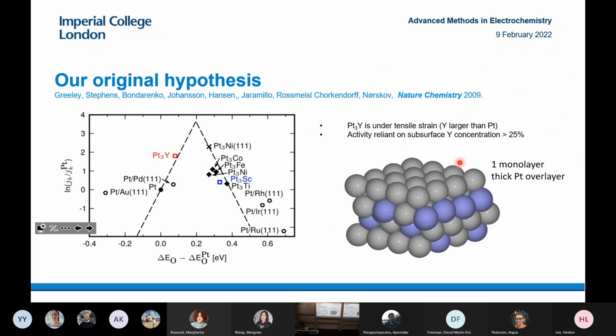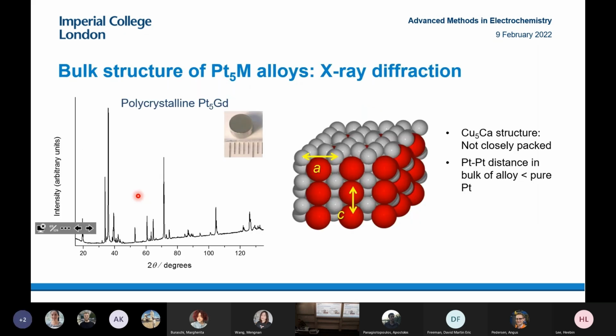So we originally expected, as I already mentioned, that this would only work if you have yttrium in the second surface layer, because actually yttrium is bigger than platinum. So we expected that if we had a pure strain effect for platinum yttrium alloys, we would actually make the catalyst less active, to go down the volcano, because you'd be pulling the catalyst apart. And we'd expect just a 1 monolayer thick platinum overlayer.